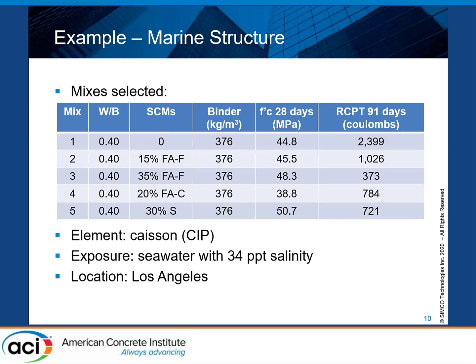So you may see larger binder contents in mixes with SCMs and mixes designed to get a good durability. In that case, the purpose was not to design, but to compare different mixes. So that's why they have all that binder content. Compressive strength at 28 days was always compliant with the requirements.